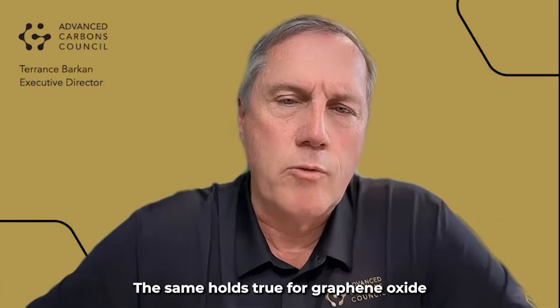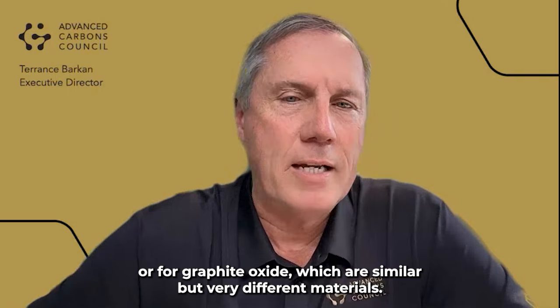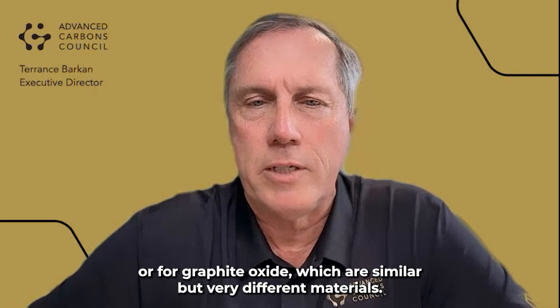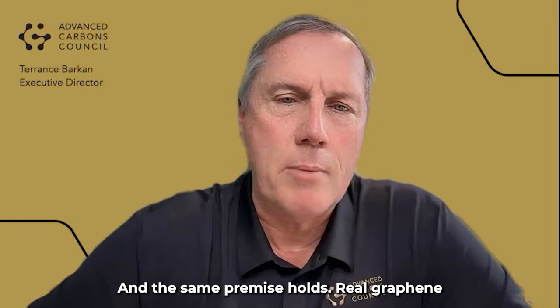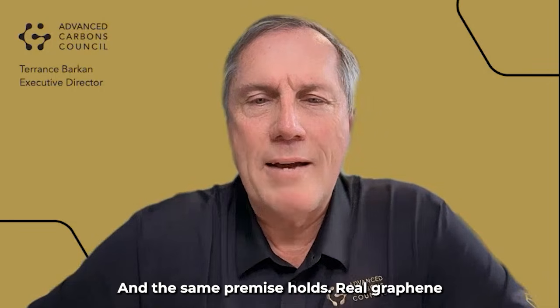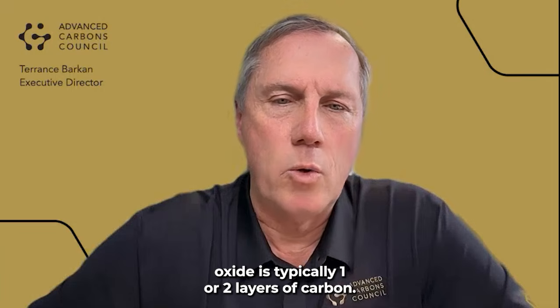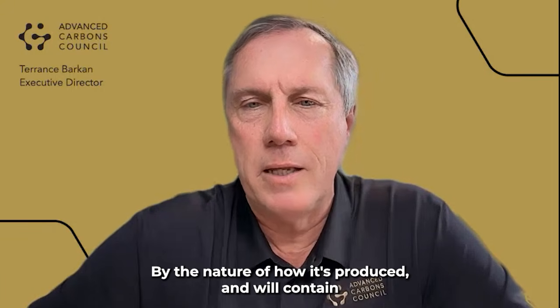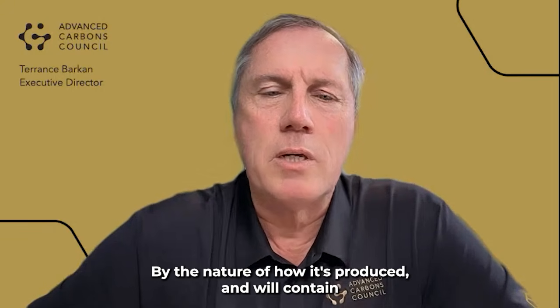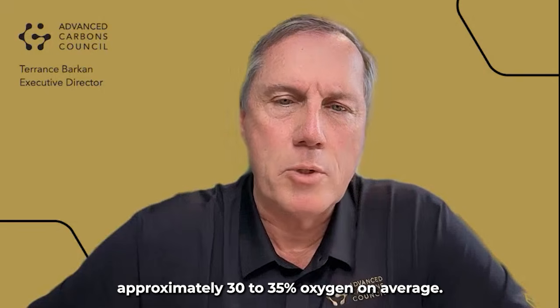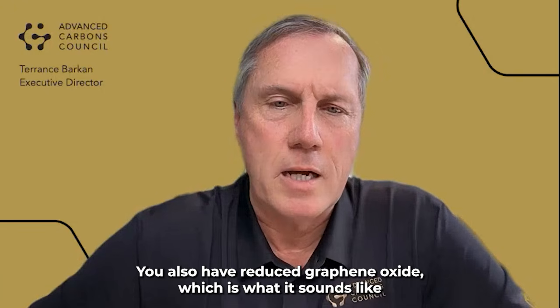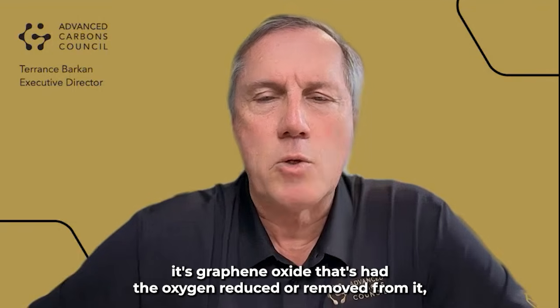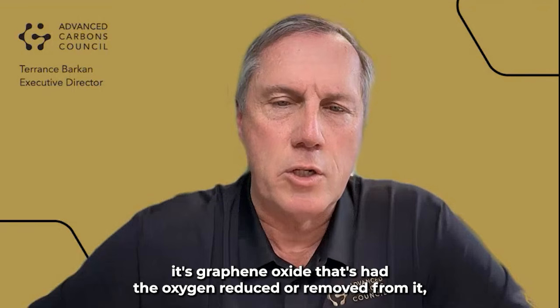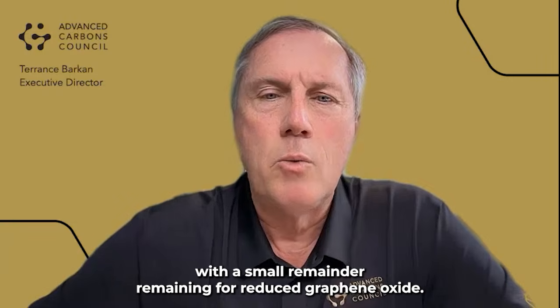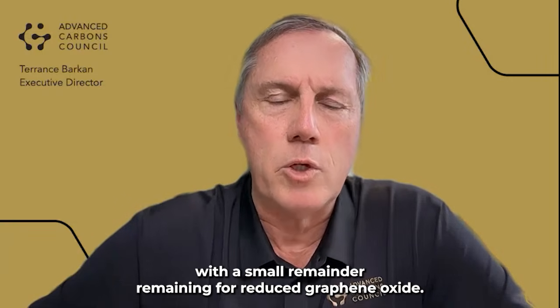The same holds true for graphene oxide or for graphite oxide, which are similar but very different materials. And the same premise holds. Real graphene oxide is typically one or two layers of carbon by the nature of how it's produced, and will contain approximately 30 to 35% oxygen on average. You also have reduced graphene oxide, which is what it sounds like. It's graphene oxide that's had the oxygen reduced or removed from it, with a small remainder remaining.